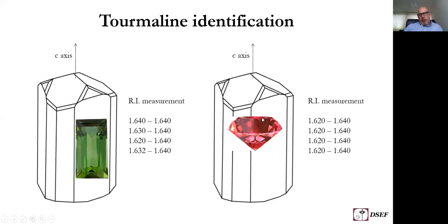Now, if you put this stone with the table down onto the refractometer, you always get maximum birefringence, because you always measure the refractive indices perpendicular to the optic axis, sorry. So the cutter has to know this so that you can orient the rough stone in the correct way.